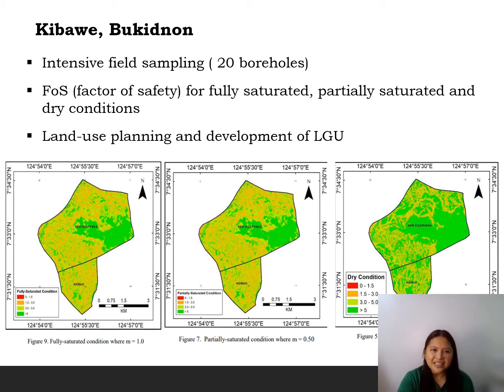And finally, the intensive landslide assessment and susceptibility maps carried out for Kibawe, Bukidnon included intensive field sampling utilizing around 20 boreholes. The result of the study revealed that the area has mostly inorganic but highly expansive fine-grained soil. It was also noted that the factor of safety has a considerable decrease when the slope condition changes from completely dry to fully saturated. The findings of the study provided a baseline reference for the area's slope stability that will be applied in land use planning and future development.